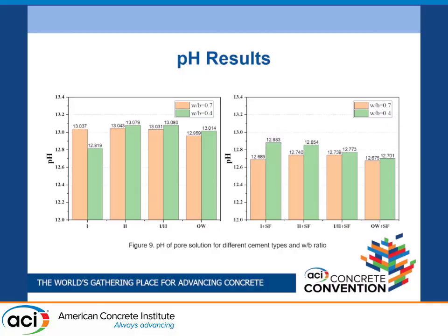The pH results basically show the pH of the pore solution, and we are trying to see the pH of the solution at water-to-binder ratios of 0.7 and 0.4. Obviously, we see that at a water-to-binder ratio of 0.7, the pH is low. This is because of the dilution effect.